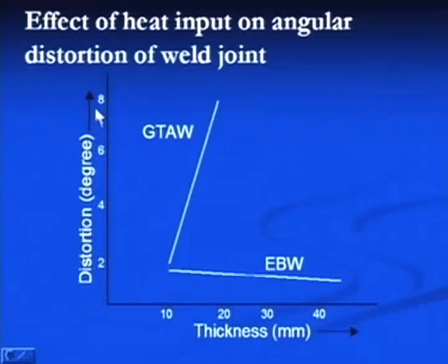the angular distortion which is noticed increases continuously with the increase in thickness of the plates in case of the GTA, gas tungsten arc welding, while in case of high energy density processes there is no significant increase; largely it decreases with the increase in thickness. So if higher thickness plates are to be welded, then the electron beam welding process would be more suitable compared to the GTA welding process, as it leads to less distortion,